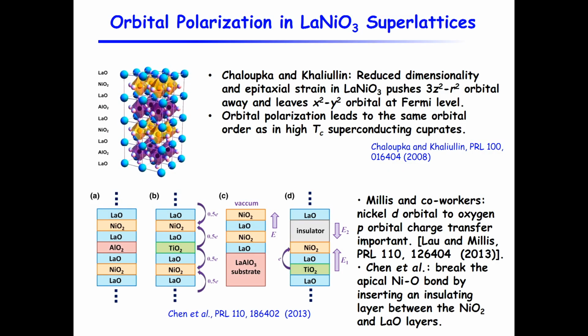The other example is lanthanum nickelate, and there is a theory that predicts that if you sandwich lanthanum nickelate between some insulator like lanthanum aluminate, you could actually separate the degenerate d orbitals at the Fermi surface to make the material have an electronic structure similar to a high TC superconductor. So if you dope it, you might be able to build a high TC superconductor from the system. And of course, there are many theoretical and experimental works.